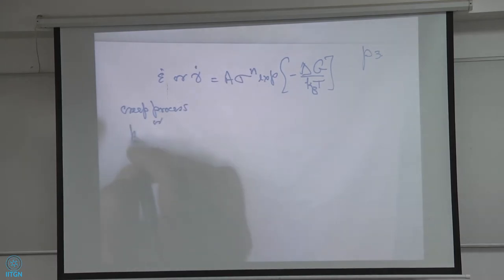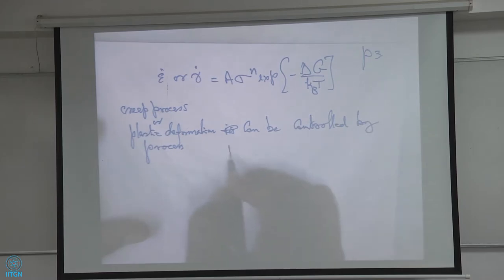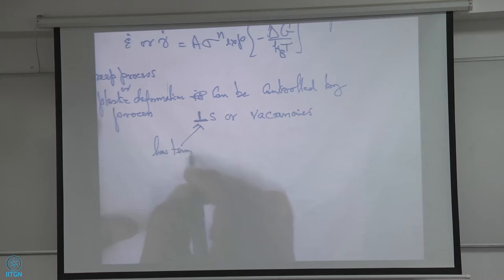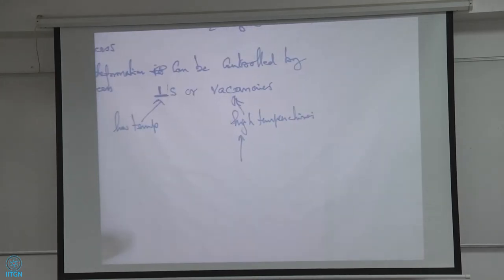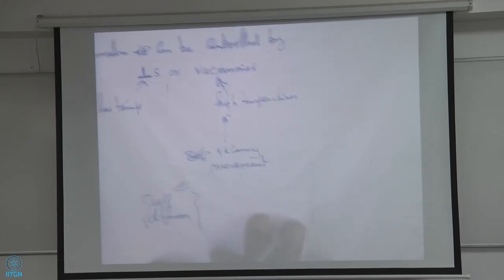This slip can take place, but if you do not have enough stress, if the stress for the decohesion of this boundary is less than the stress it takes to transfer the slip, then the fracture would take place. Otherwise, the slip would take place. When we do the crystal plasticity models, those are the kind of things we answer usually from the modeling. Will the slip take place, or will the decohesion take place? What are the statistical numbers and all that? If we have time, I may touch upon it a little bit.